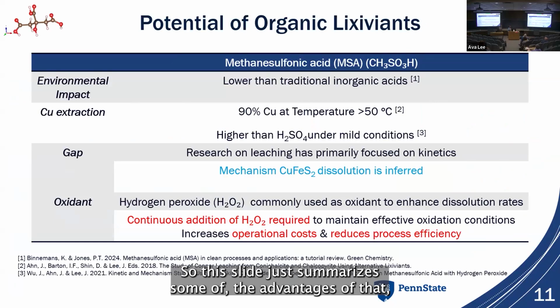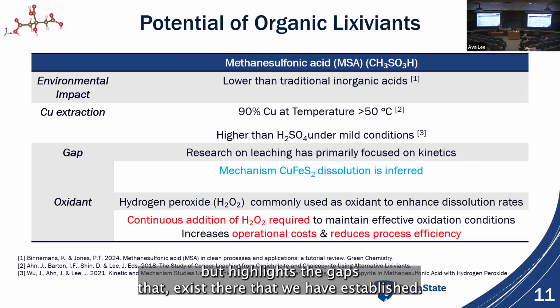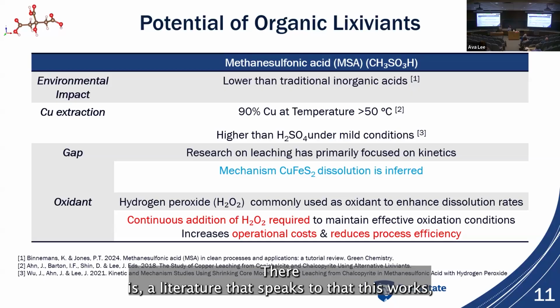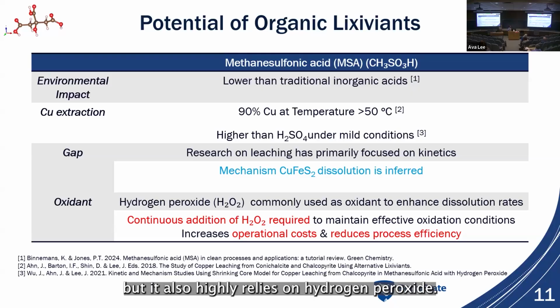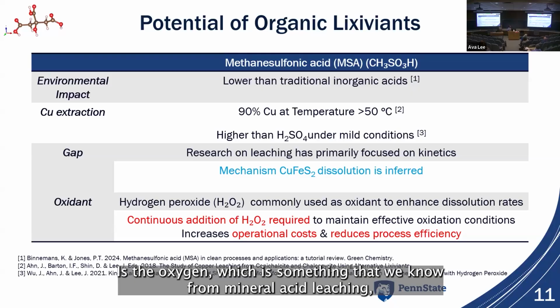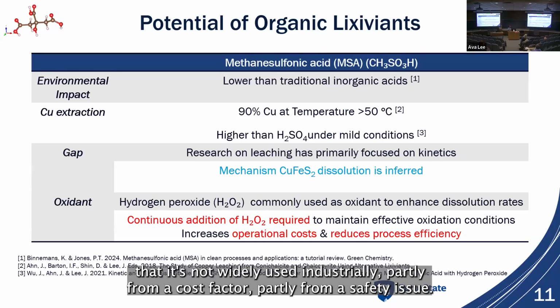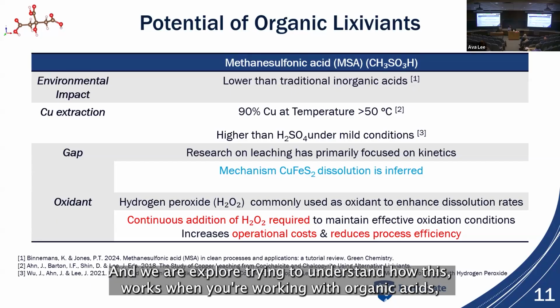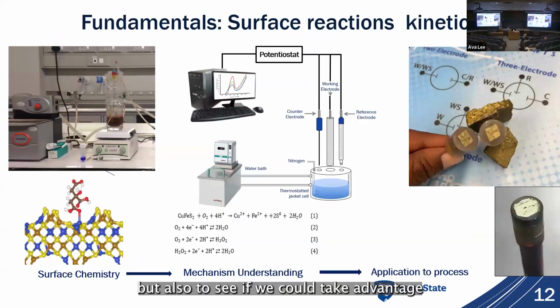So this slide just summarizes some of the advantages of that, but highlights the gaps that exist there. We have established there is literature that speaks to that. This works, but it also highly relies on hydrogen peroxide as the oxidant, which we know from mineral acid leaching is not widely used industrially, partly from a cost factor, partly from a safety issue. And we are exploring to understand how this works when you're working with organic acids, but also to see if we could take advantage of the traditional cuprous or ferric ferrous redox couples in our systems.